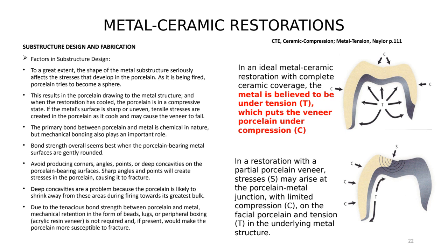Avoid producing corners, angles, points, or deep concavities on the porcelain-bearing surfaces. Sharp angles and points will create stresses in the porcelain, causing it to fracture. Deep concavities are a problem because the porcelain is likely to shrink away from this area during firing towards its greater bulk or thickness.